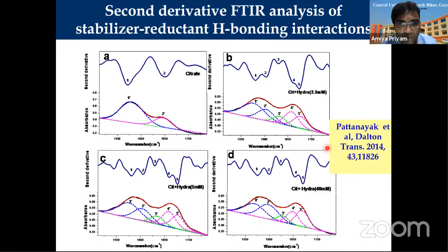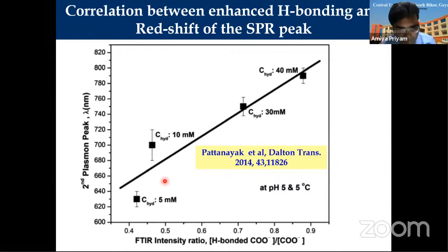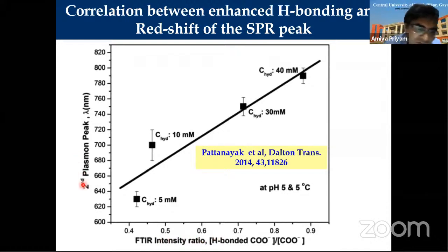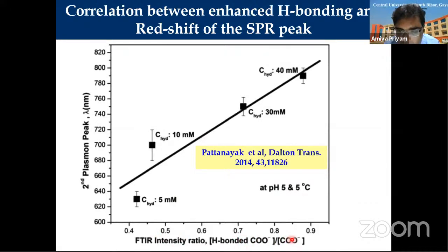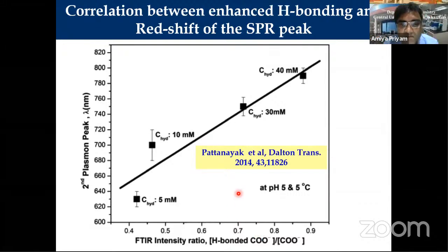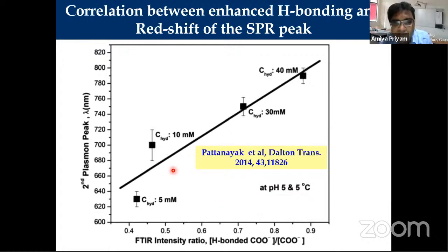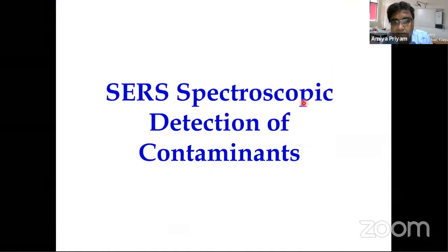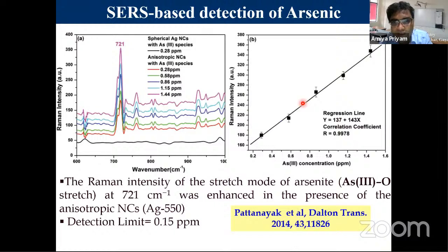We could analyze the hydrogen bonding interactions also between the stabilizer and reducing agent, and then an empirical relation was also found out. So you can see on the y-axis we have the shift in plasmon peak position versus the FTIR intensity ratio of the hydrogen bonded CO and non-bonded CO. That gives a measure of the extent of hydrogen bonding interaction in the system, and we could establish that as the hydrogen bonding increases, the plasmon peak is shifted to the red side. So now I'm moving into the applications.